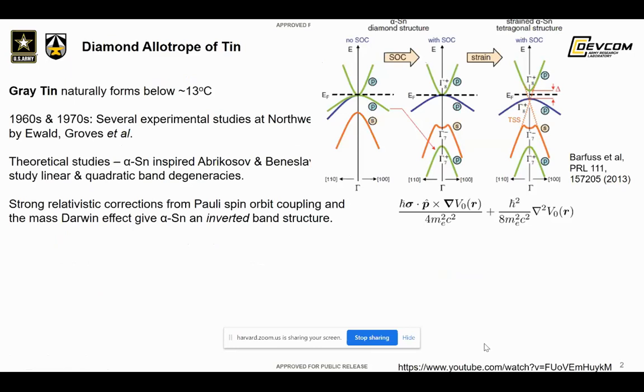This is a diamond allotrope of tin. It grows naturally below 13 degrees centigrade in bulk. However, in 1987, MBE growth of alpha tin was achieved, and this allowed stable films to be formed at up to around 100 degrees C, if grown on CdTe or indium antimonide substrates.